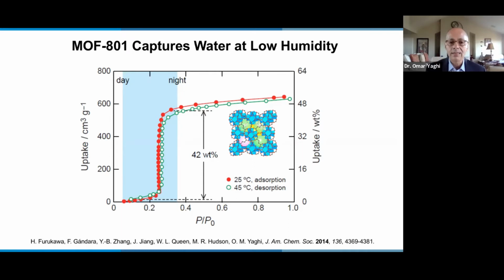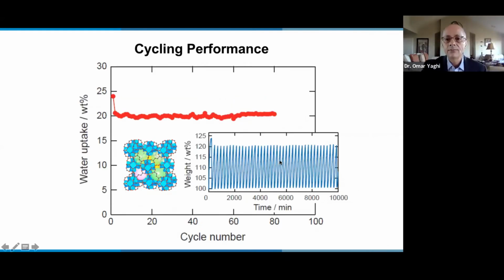So the shape of the isotherm indicated to us that there is, unlike any other material, a cooperative phenomenon going on in terms of binding water into the pores. So we tried to recycle water to make sure that the material is stable. And you can see here 80 different cycles with absolutely no imprint left on the MOF in terms of its performance. Except we saw that after the first cycle, the material lost just a tiny bit of its performance, just a few percent. Then we have a constant performance. This meant that some of the water that goes in first is actually staying in the pore.